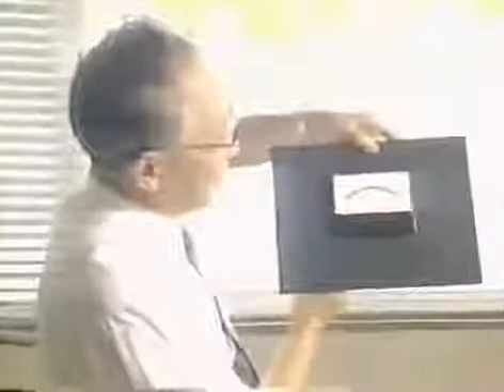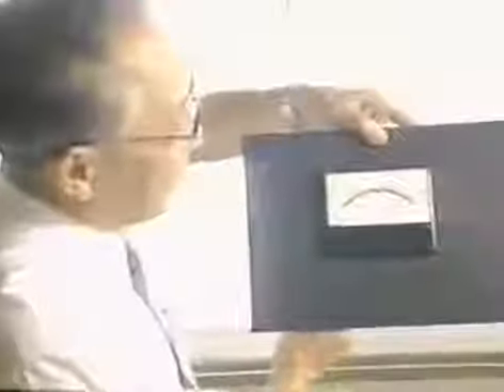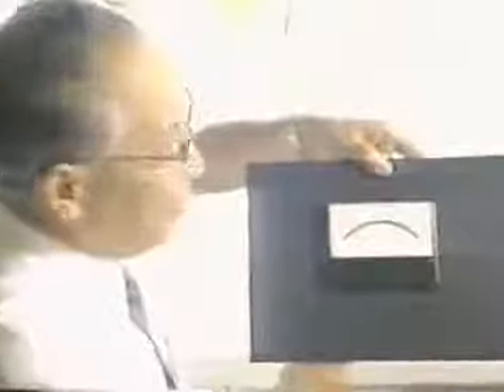Another important point is that when the temperature has been raised to almost 1,000 degrees centigrade, if you let the temperature act naturally, it rises and falls. That also is wrong. You have to keep the temperature fixed. Although I say fixed, there still is slight fluctuation. But this was kept at 0.1 degrees centigrade in the American specifications at the time. That's tremendous control. When the temperature rose, the needle of the gauge shook.